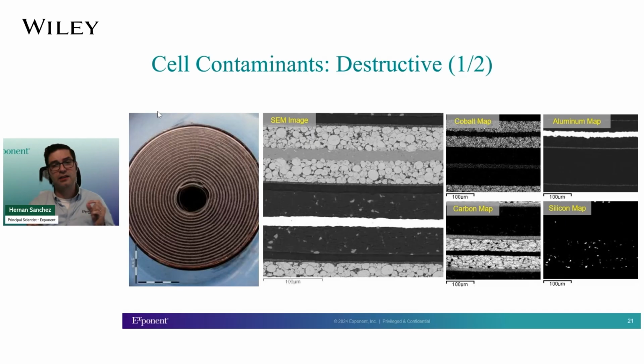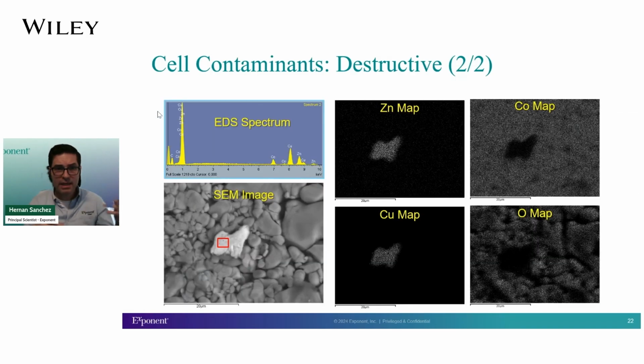So those are things where destructive testing is very useful. And the cross-section is very useful for understanding the distribution of said particles, whether it's just a surface contamination or something more like in the mix of the negative material in this case. But back to the examples of the loose particles, either by cross-section or by cell teardown and tracking them down, you can find the composition of those contaminants, and you can use that to track down the source of the contaminant.